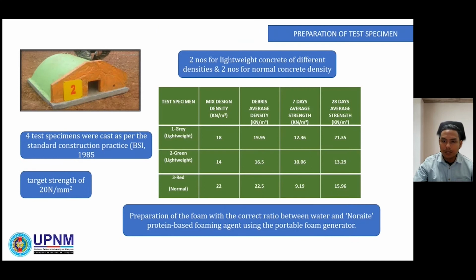The preparation of test specimen. In total, 4 test specimens were cast: 2 of lightweight concrete of different densities, and 2 of normal concrete density. The preparation of the specimens was per the standard construction practice of British Standard. Before the casting, some trial mixes were conducted based on available data from records to achieve the target strength of 20 Newton per mm square.